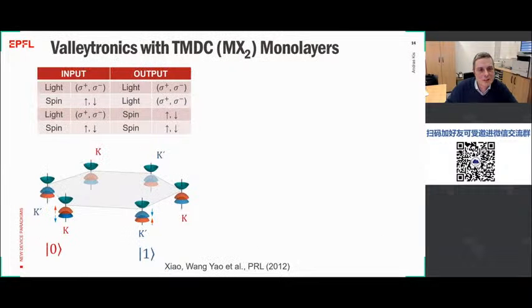And then finally, an additional alternative scheme to electronics that could be possible using 2D materials and semiconductors is the so-called valleytronics, which is based on the basic physics and the band structure of 2D transition metal dichalcogenides, in which in the single layer limit of materials like MoS2 or tungsten diselenide, you have broken inversion symmetry, and you also have strong spin orbit coupling due to the large mass of constituent atoms. And this gives rise to this characteristic splitting of the valence band, which in the different corners of the Brillouin zone will have different signs.